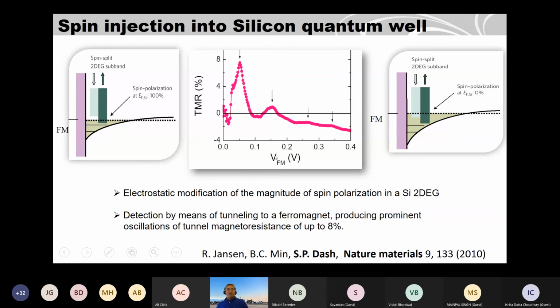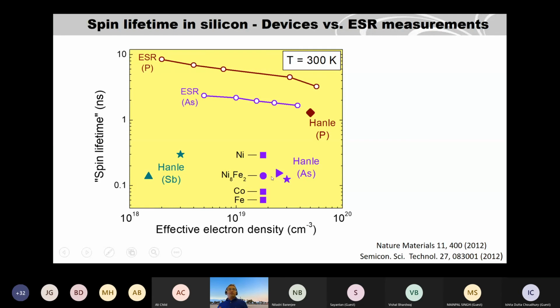Okay, so far so good. So we could inject spins and detect spins in the semiconductor. But what about the lifetime? How is this compared to electron spin resonance experiments in semiconductors? So actually, it's orders of magnitude less than what we see. In our measurement, our lifetimes are less than a nanosecond. But in ESR, electron spin resonance experiments, it's a few nanoseconds or up to 10 nanoseconds.